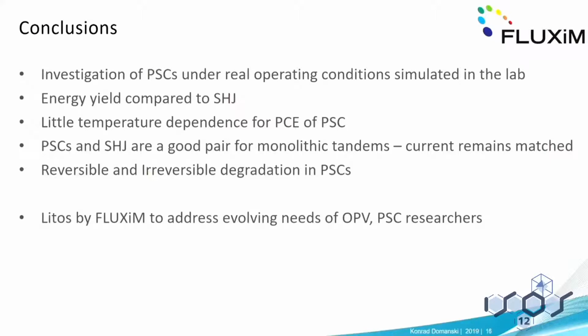We see little temperature dependence for perovskite solar cells, unlike for silicon. Silicon and perovskite are a good tandem pair because once you match the currents, they remain matched. Although I have to say we didn't look at the spectral variations throughout the day in the study, I have to give you that. And we see reversible and irreversible effects in perovskite solar cells.